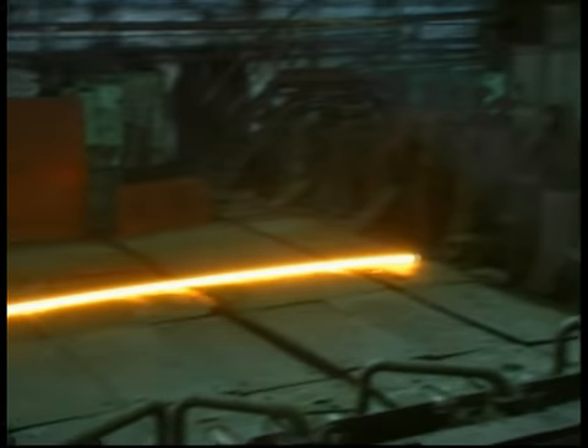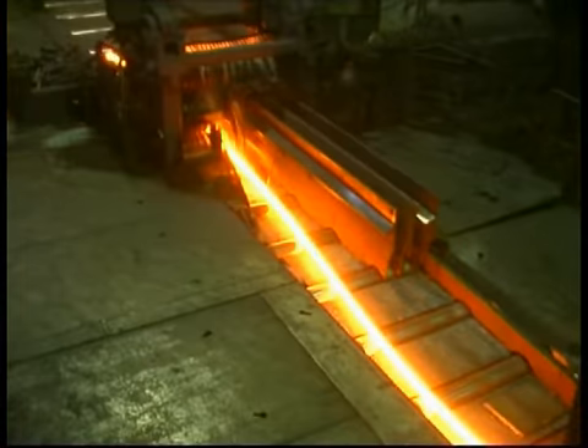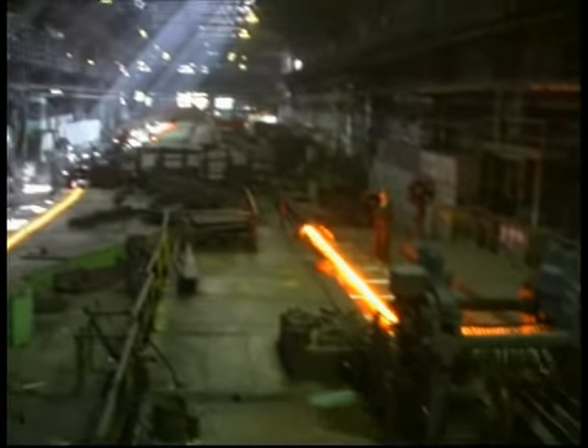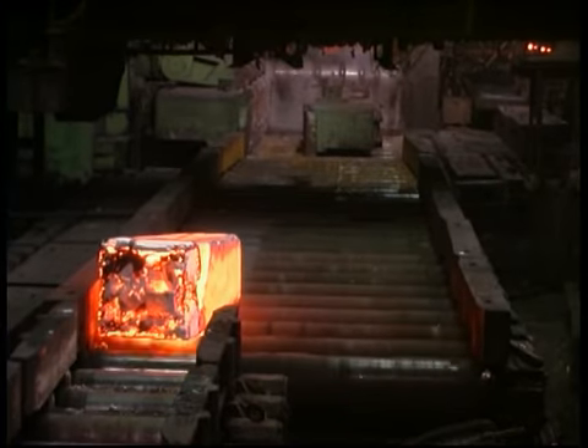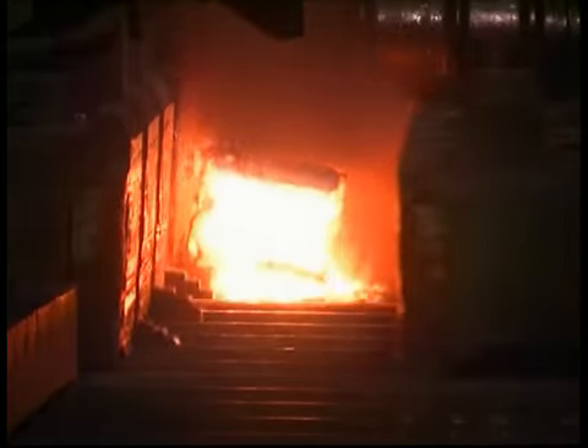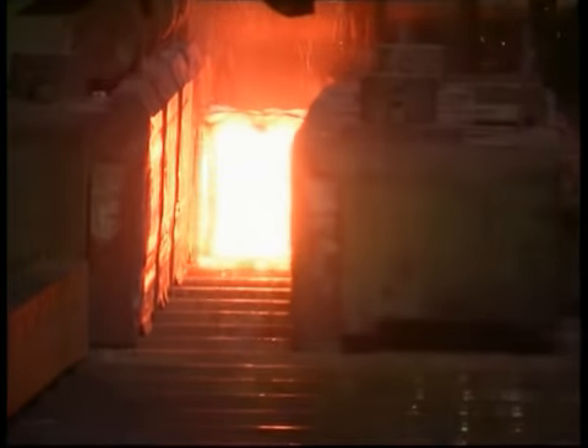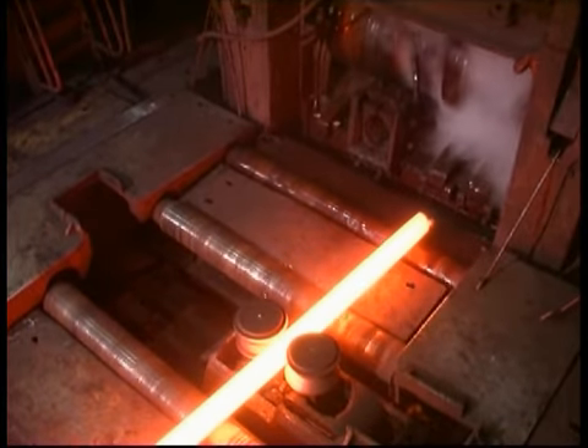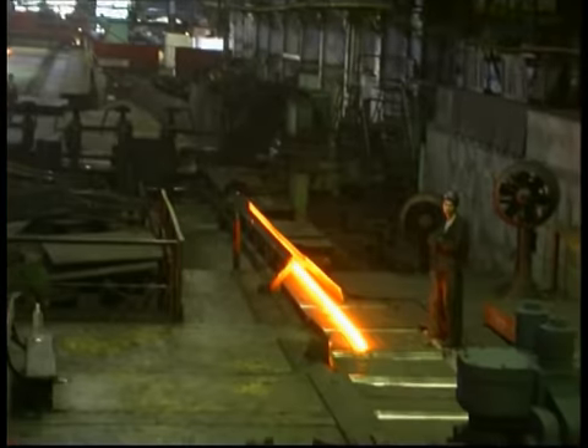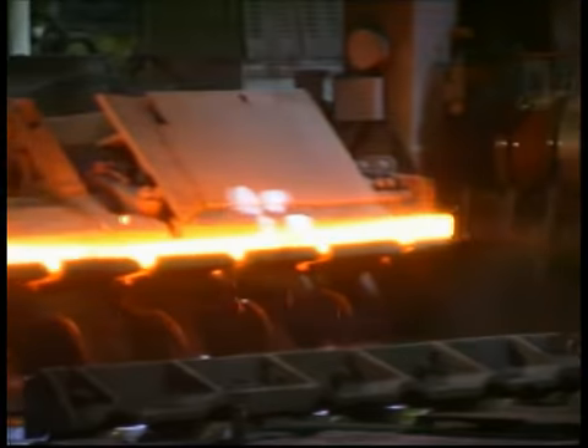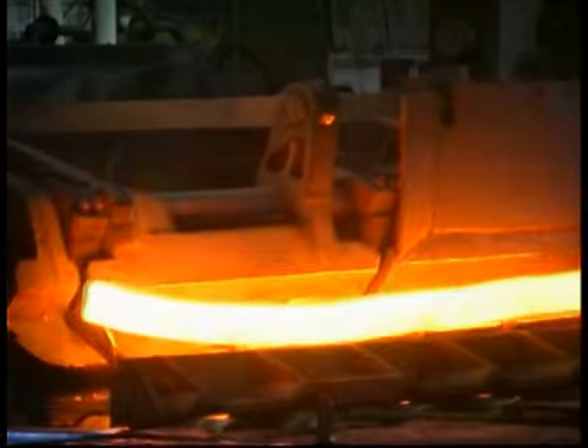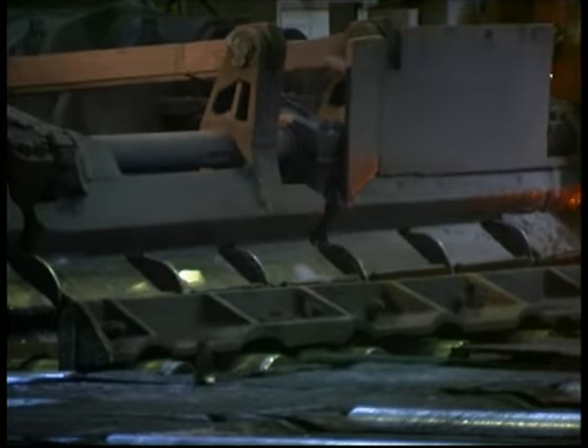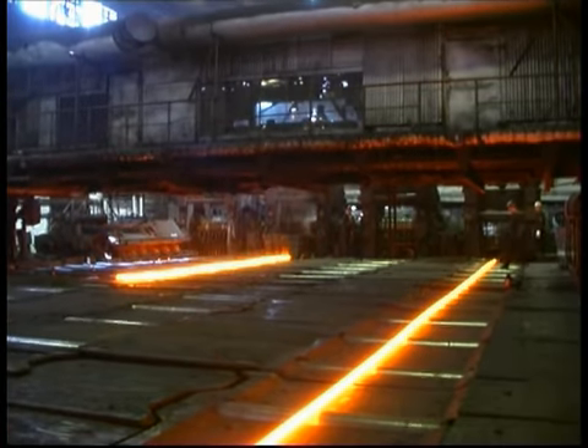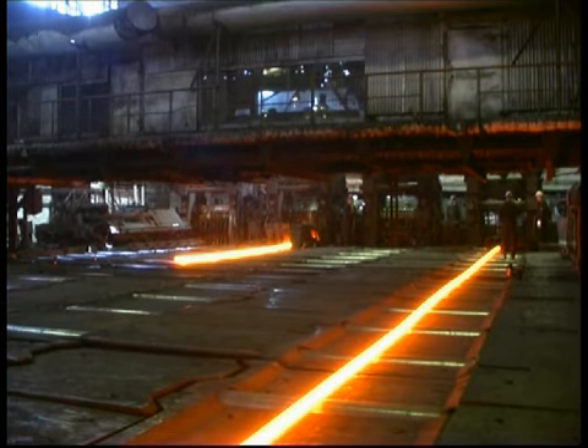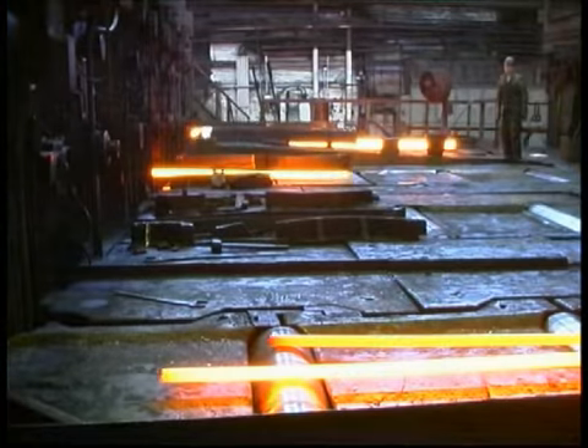The rolling facilities of the Dneprospettstal works consist of 4 rolling mills, equipment for ingot heating, cutting, flattening and bar turning. Rolling of ingots 2.8 to 7.4 tons in weight for section mills, and producing of roll stock 130 to 300 millimeters can be processed on the 1050 roughing mill. Round and square roll stock of 8 to 130 millimeters in section, flats, bars with parabolically shaped edges and trapezium section bars are produced on section mills 550, 325, 280, following the intensive scheme.